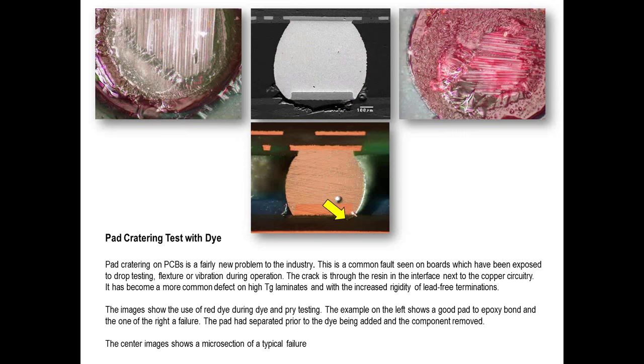But basically, separation of the pad, the copper pad, from the laminate surface has been seen with certain laminate materials, which have a lower peel strength or cannot stand up to mechanical force applied to them. So during heating and cooling of big boards with big BGAs on, we're actually putting a lot of stress on the weakest point, which is the pad to laminate interface.